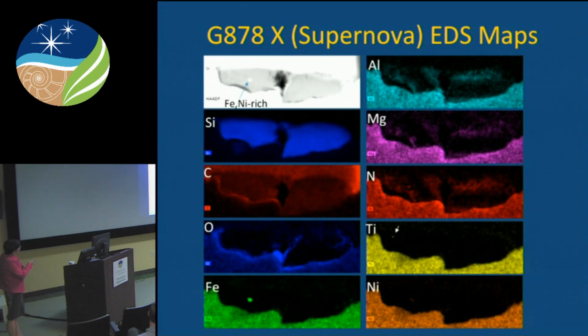All right, so the compositional maps of this grain show major elements are silicon and carbon. There's also iron rich, so there's the iron subgrain. It's got a little bit of nickel, you can probably just barely make out. There are also titanium, and there's aluminum nitride-rich grains. Interestingly, there's magnesium that's distributed all across the grain that spatially correlates with the aluminum.